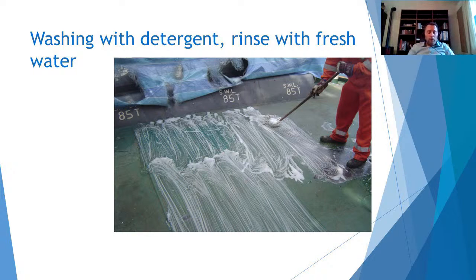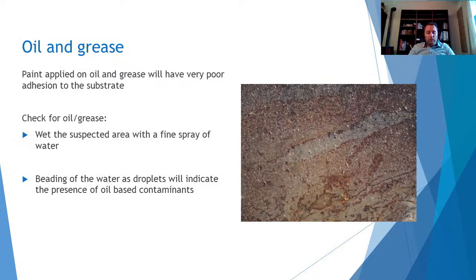Oil and grease. Oil present in small quantity on a black skin surface may be detected by this test. Pour the solvent across the surface. The solvent should form a continuous flow and not be broken into droplets. Use an ultraviolet light to illuminate the surface to reveal traces of certain hydrocarbon oil, grease, or fingerprints. Ultraviolet light also may reveal other material on the surface, which may or may not be detrimental to the coating.